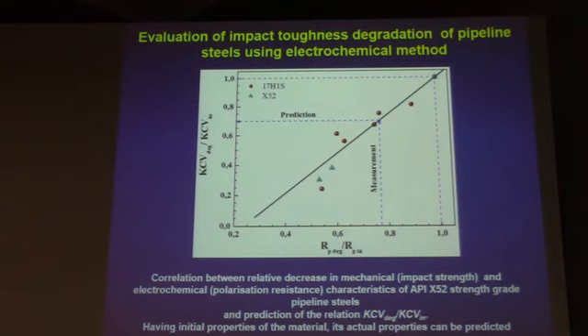caused by their in-service degradation. And this correlation enables an evaluation of bulk material properties changes by determining changes in their electrochemical characteristics. So it should also be noted that only relative changes in these characteristics correlate between themselves, but not absolute values of these parameters. And to use this correlation in practice, we need to know the initial mechanical properties of the material as well as initial electrochemical characteristics of this material. And the problem is resolved when there is a metal in the initial state, for example, reserve pipe in the case of oil and gas pipelines.